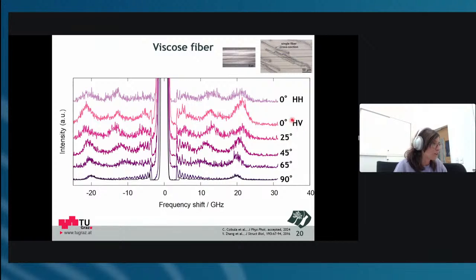When we then put in the cross polarization, we got a third bump, which at least was possible to identify as a transverse mode, because it's not really visible here. So at least we got that. And then as we went along, we could see that this third peak here at 20 gigahertz would also give a very ridiculous sound velocity, which would not make sense. If you compare to literature of wood, it would be way too high. And this peak was barely moving. So when we went through all these orientations, we were puzzled that this peak would just stay here.